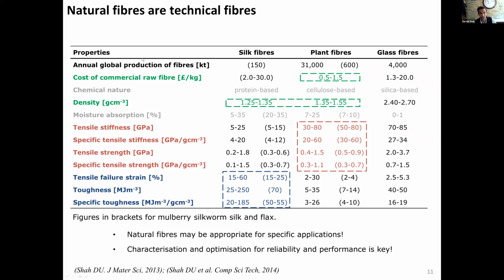And nevertheless, natural fibers are technical fibers, and apart from their low density and impressive vibrational properties, you can get quite impressive tensile behavior. In terms of stiffness, you can achieve up to 80 gigapascals, and even strengths of 800 to 900 megapascals, about half that of glass fiber, relatively easily. Silk is another fiber we are interested in, which is useful for more toughness-critical applications.